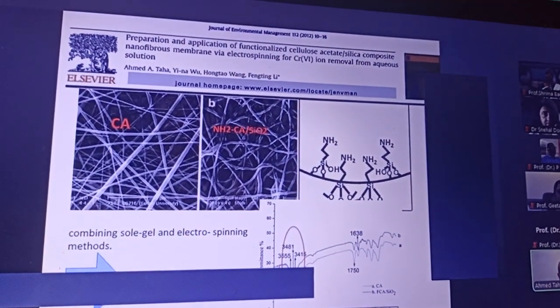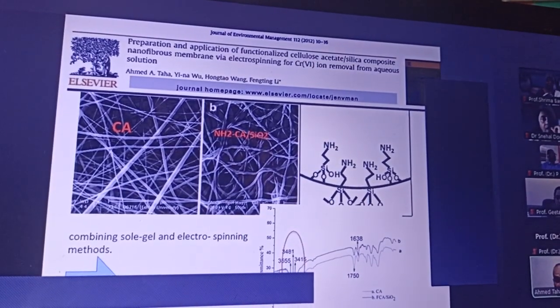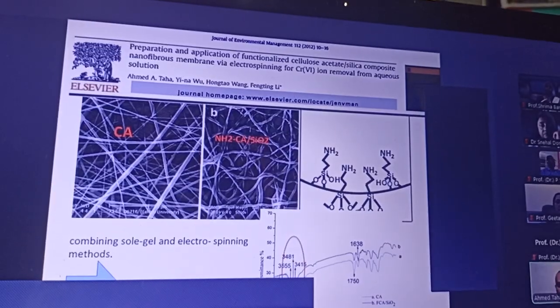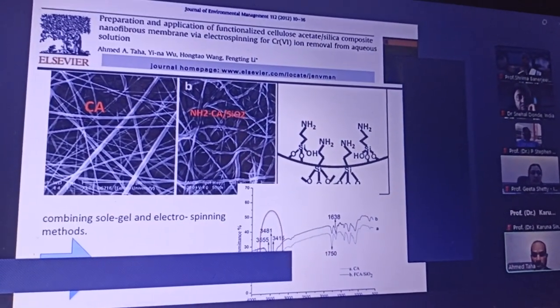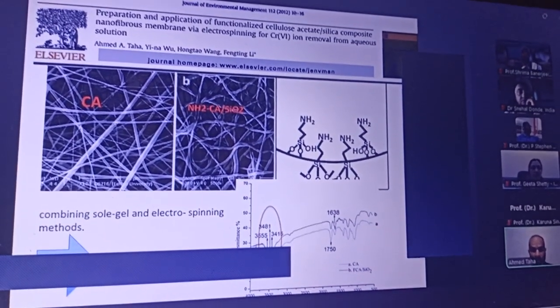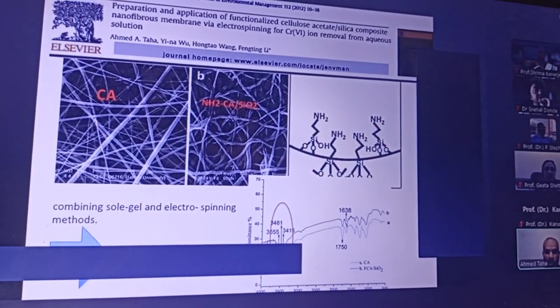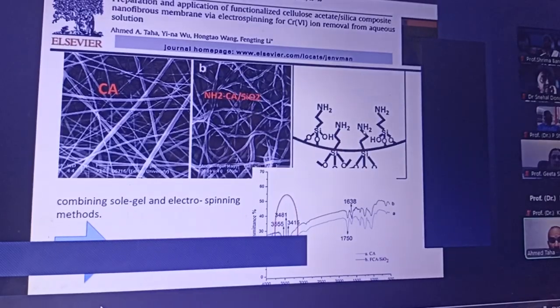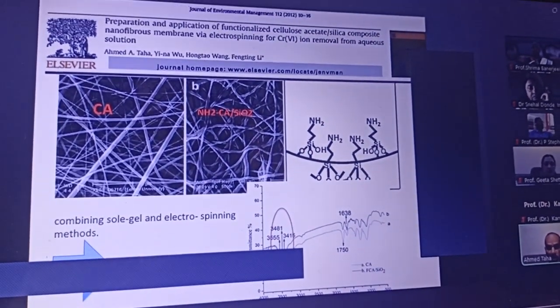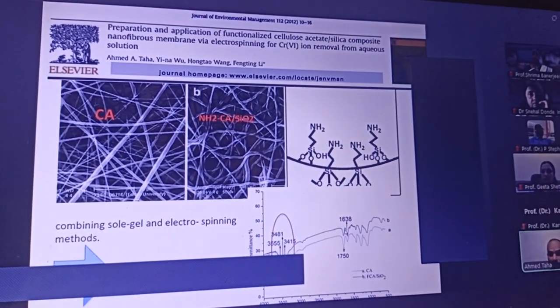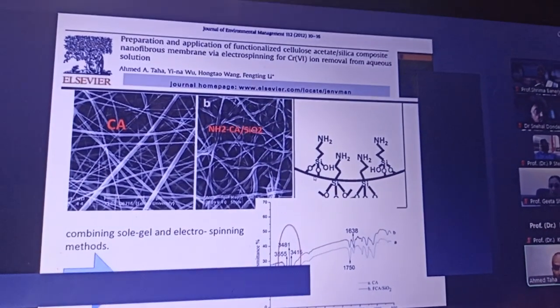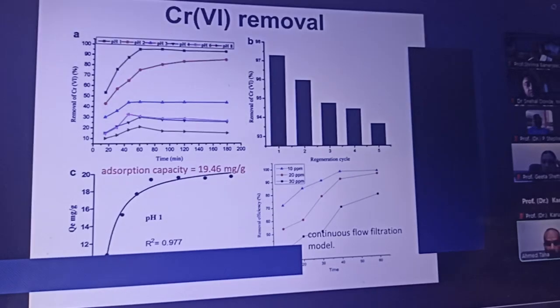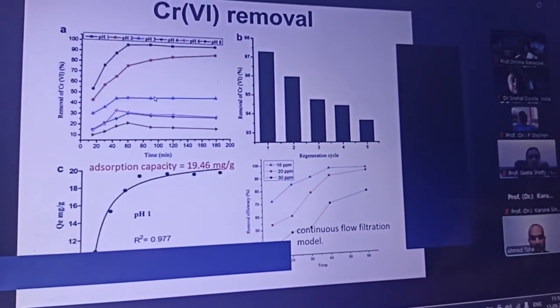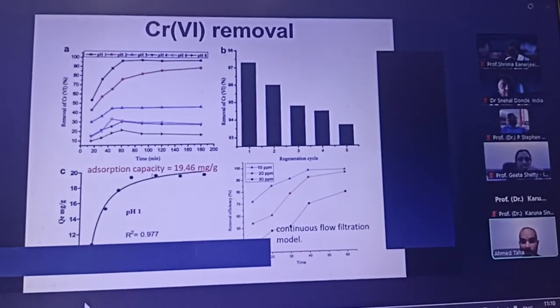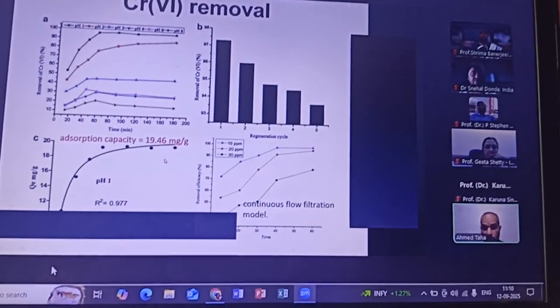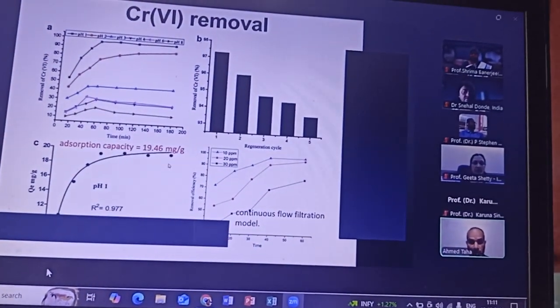In another work, we tried to find a naturally existing organic polymer and functionalize it and improve its surface area. We got cellulose, a very common polymer that comes from plants. We took that polymer and added amine functional groups to the surface, and did some post-treatment to improve the surface area. The functional groups were confirmed by characterization; this is the FTIR that tells us the functional groups are there. We also studied how this material behaves at different pHs, and we studied the removal capacity. This was about 19.46 milligrams per gram.